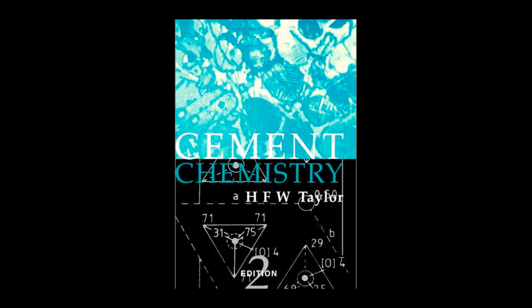So when we analyze a finished clinker, the maximum amount of magnesium that didn't form that problematic periclase is often contained right here, inside the structure of the key strength giver. It's a really elegant way for the system to manage these otherwise dangerous elements. And the aluminum and iron ions compete for these substitution sites, and their presence is what shifts the C3S structure from one polymorph to the next, for instance, stabilizing the monoclinic forms, which are slightly more reactive than the triclinic forms, though all of them are highly reactive compared to belite. That structural sensitivity is just incredible.